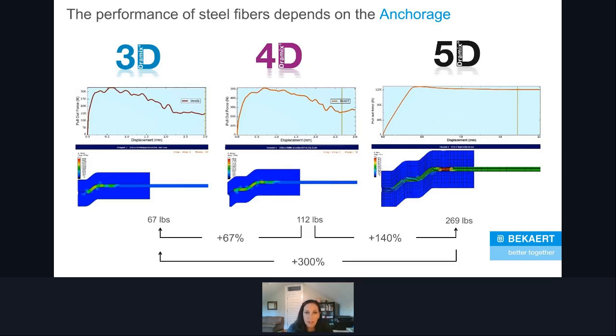By contrast, with 5D, it has that extra hook and that ultra high strength steel. So in this case, we actually achieve perfect anchorage, and the failure of a 5D fiber is going to be in the form of yielding of the steel itself. Again, that 330 KSI and 6% elongation capacity. It's also worth noting here that as a result of this, 5D fibers have a compatibility requirement of the strength of concrete that you're using. If you use a concrete that is too weak, then it won't be able to develop that anchorage that it's required to fail this way. So we just want to keep an eye on using appropriate strength concrete for that fiber.